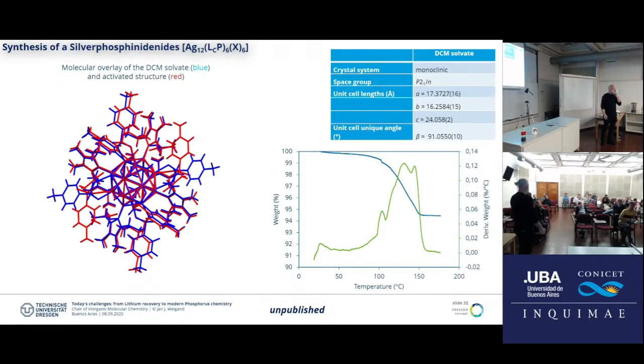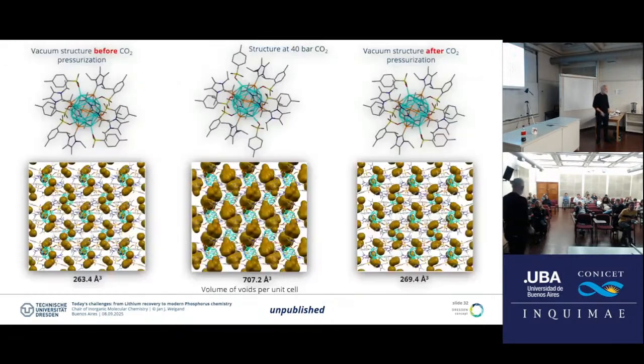Now, working together with Len, he is a specialist on putting gases into porous materials. So we looked into gas absorption, and quite interesting is this is the activated structure after DSC when we take out all the DCM, and then you see very small voids. So you see the tosylate is like this here, yeah? So then when we pressurize CO2 at 40 bar, this tosylate opens or rotates by 90 degrees and the voids become quite big. So we change the void by a factor of 3. And the void is filled with approximately 2 CO2 molecules.